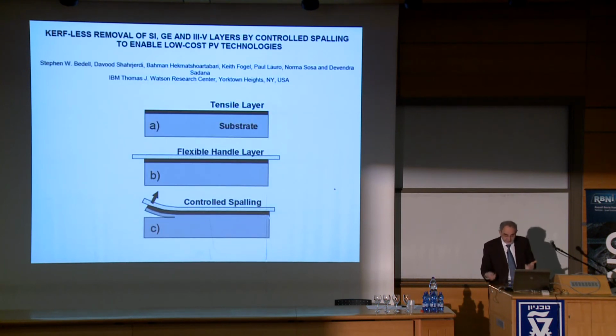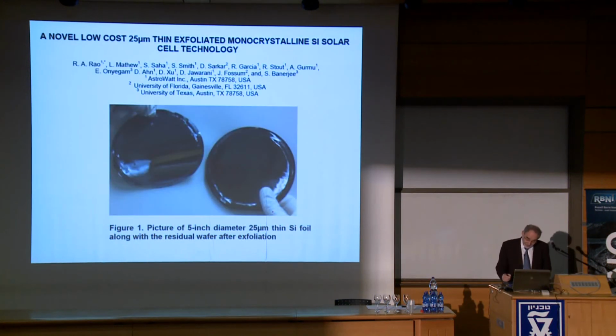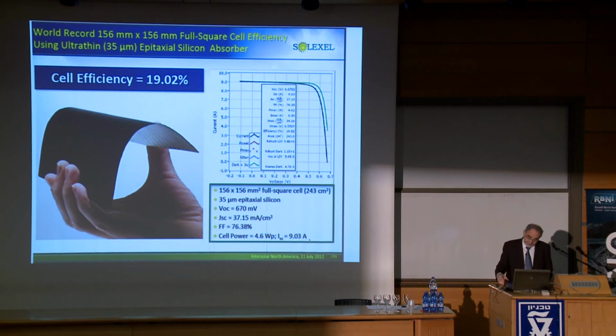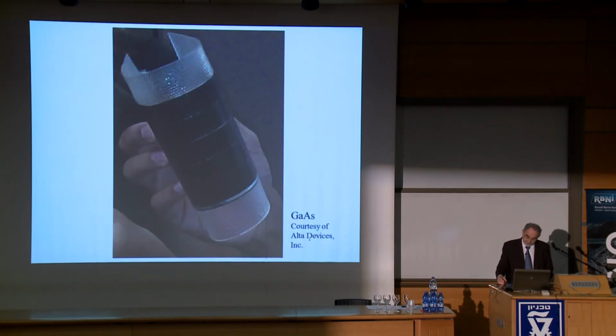But this idea of peeling crystalline films, I've always liked the idea. It's now being adopted in silicon, and this is called spalling. This is from IBM, who's not a small company, where they're actually peeling the silicon. And so this is an idea that extends beyond gallium arsenide. They crack the silicon film, and it comes off surprisingly uniform, about 30, 40 microns thick, which is a good thickness for silicon. Similar work from a startup company in Texas, where they peel the silicon wafer. So I have my flexible gallium arsenide, but they have their flexible silicon foils, and they call it exfoliation. It all means the same thing. And there's another company here using Smart Cut, which is sort of an ion implantation. They can peel the films. And everybody's always amazed at how flexible single crystals can be. And this is for gallium arsenide.